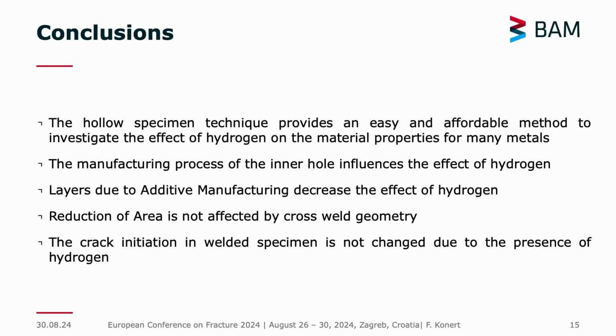So as conclusions, I just want to say, and as you heard this week many times, in my opinion also, the hollow specimen technique provides an easy and affordable method to investigate the effect of hydrogen on the material properties in many metals, and the manufacturing process is really a crucial point you should keep an eye on. Layers due to additive manufacturing decrease the effect of hydrogen, at least for the test conditions we performed here, and the reduction of area is not affected for the cross-weld specimen we saw here, which is also related to the same microstructure where the crack happens. And the crack initiation in the weld specimen is not changed by the presence of hydrogen.